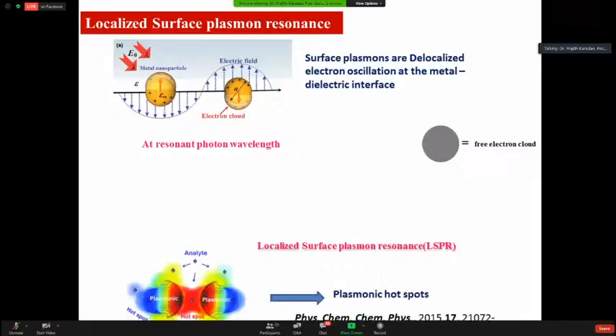If you bring two metal nanoparticles closer, to less than 10 or 5 nanometers, then the point in between the nanoparticles will experience a much higher, the highest, electromagnetic field, because of the interaction of the electromagnetic field associated with the first nanoparticle with the second nanoparticle. This point, where it experiences a higher electromagnetic field, is known as a plasmonic hotspot. So now we know what surface plasmons, localized surface plasmon resonance, and plasmonic hotspots are. These are the basics of surface enhanced Raman spectroscopy that we are going to discuss.